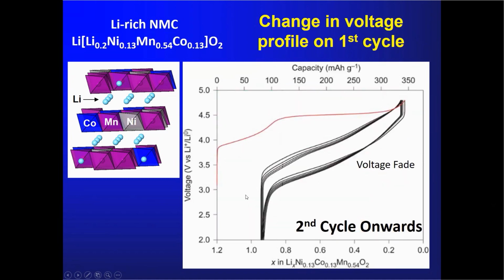Now, if you keep on cycling, you get the black curve. So you still get some hysteresis. In fact, this is what I would call real hysteresis, because a hysteresis loop goes round like this. We talk about hysteresis on the first cycle. It's generally a term used, and I will use it for that reason. But in a sense, it's not really hysteresis. It's irreversible voltage loss. You never get it back, as you can see here. So, of course, you could operate in this region here and accept that loss of the high voltage and therefore the higher energy that one could get from the cell. But ideally, one would like to cycle along this region here, where you can actually access the high voltage and higher energy density. So the problems you can see are writ large here.